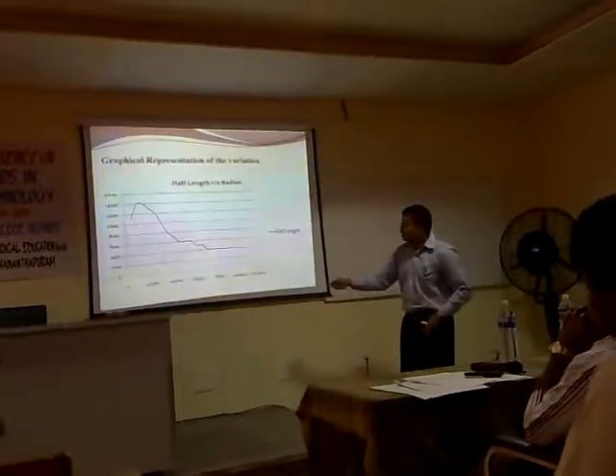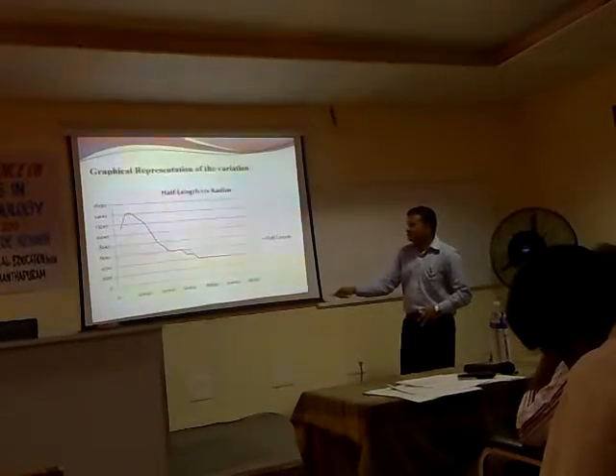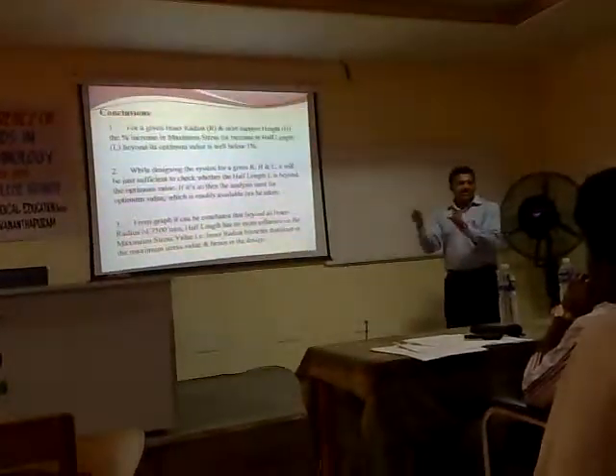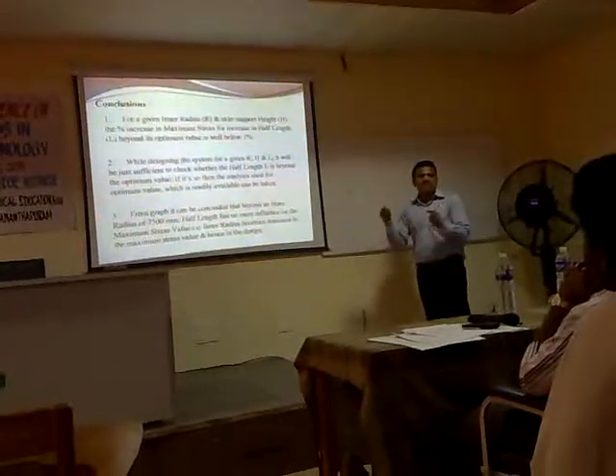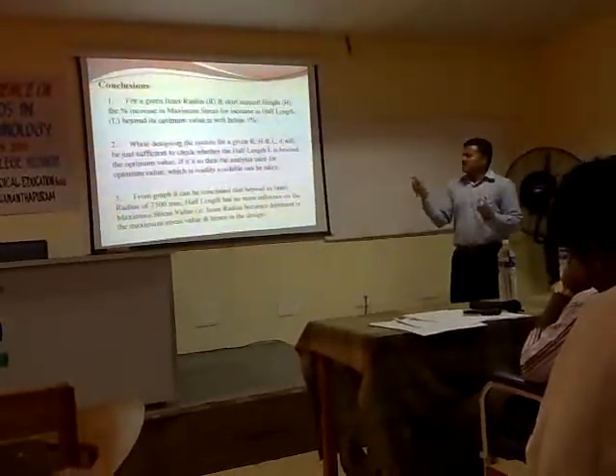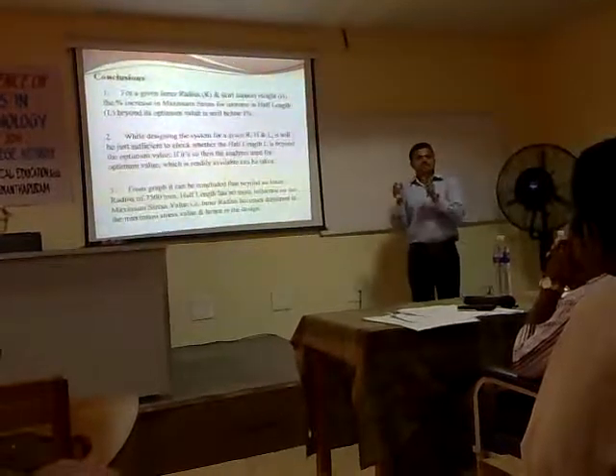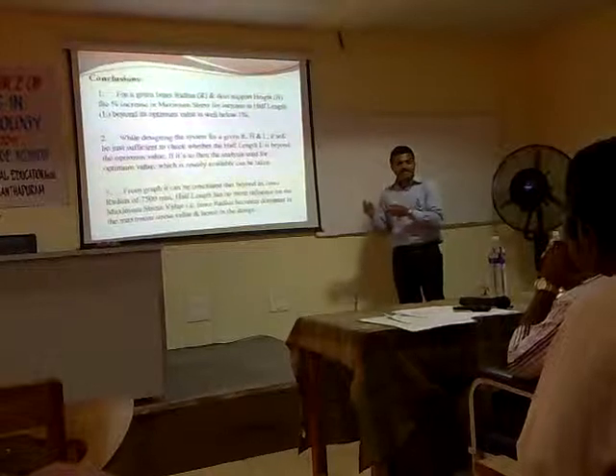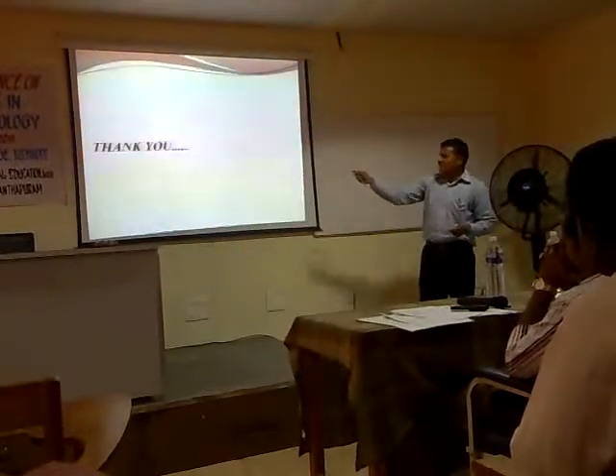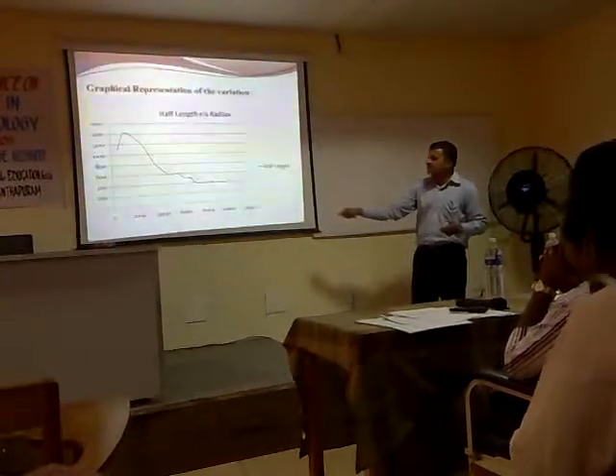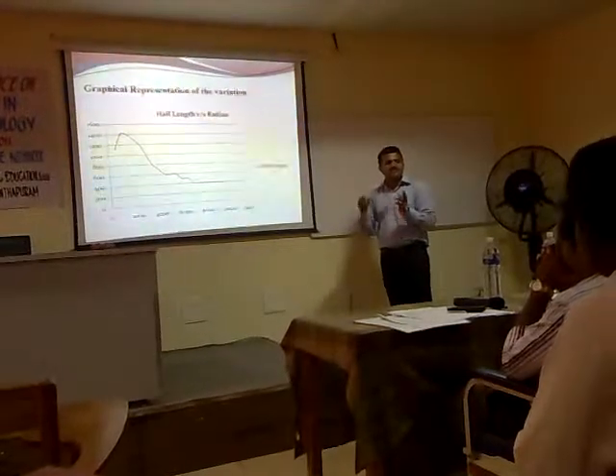Now I have plotted this. I have varied the radius, and for each radius I have plotted the optimum half length, and beyond a particular value, say 7000 mm, I am getting a very constant optimum value for the pressure vessel. So from this I can conclude that for a given R by H ratio, I can restrict the value of half length so that I get only a 1% increase in stress value. While designing the system for given R, H and L, I will just check if the given half length is beyond that optimum length. If so, then I can directly take the stress calculations. From this graph I can conclude that beyond 7000 mm the main contributor to the stress is the radius of the hemispherical vessel and not the half length of the pressure vessel.